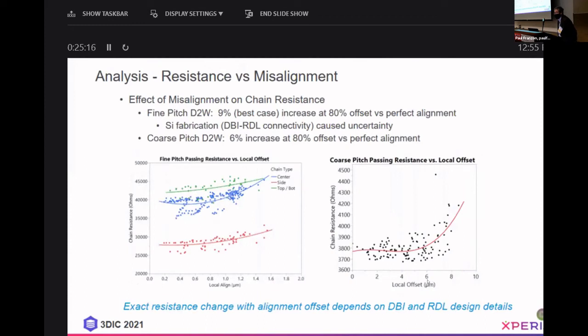This data here shows the effect of misalignment on our chain resistance. This is the resistance of the entire chain, and we're only seeing about a 9% change in the case of the fine pitch with the 80% misalignment, and with the coarse pitch, we're only seeing about a 6% increase with this 80% misalignment. So the misalignment of the DBI copper to copper interconnect is causing a relatively small change in the overall chain resistance. Of course, the exact value of this would depend on the details of the DBI and RDL designs.